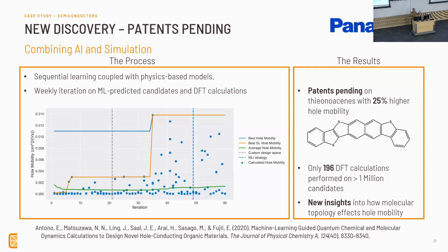We switched to a much broader space of all known molecules. And once we got a little crazier with that, the machine learning model started to predict a lot more diverse sets of molecules to test. That's when we got outside of a local minima, if you will, about where people have already looked for these kinds of things, and found something really novel.